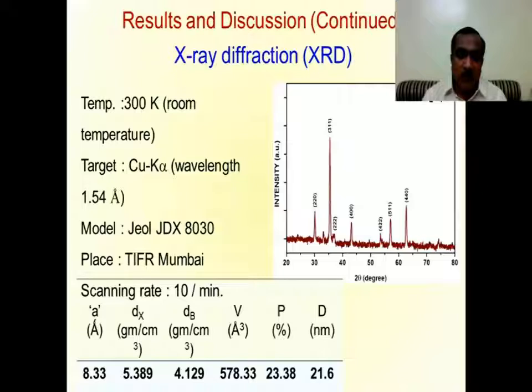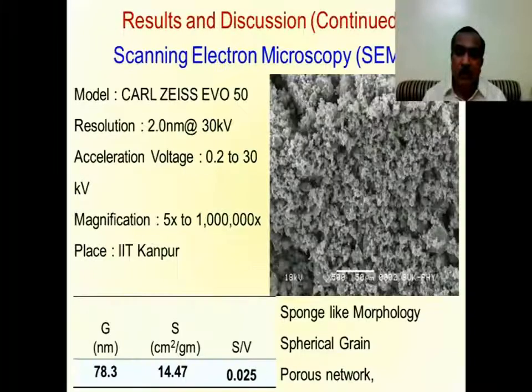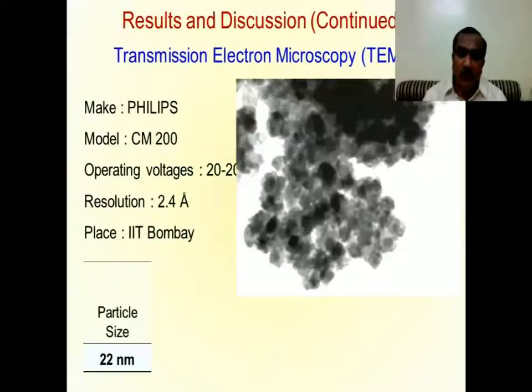The X-ray density, bulk density, volume, porosity, and the particle size were obtained with the XRD parameters. Here, the particle size is more important, and you will observe that the particle size D is 21.6, that is almost 22 nanometer. So the prepared particles are in the nanoscale dimension, or it is a nanoparticle. Secondly, for the morphological study, we use the scanning electron microscope, and a photograph of the scanning electron microscope is shown here. Using the same images, we can find out the surface area as well as the grain size. All these are important to establish that it is a nanoparticle.